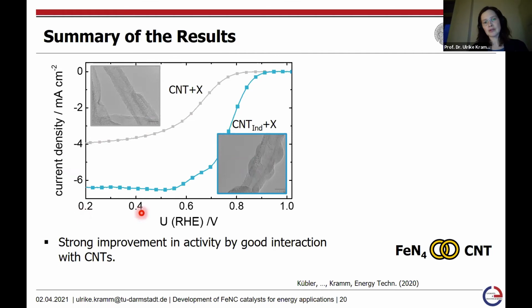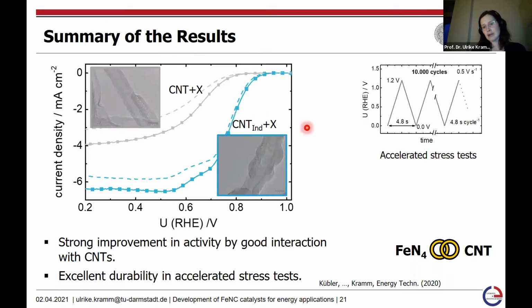For the oxygen reduction reaction, we have a standard potential of 1.23 volts, and that means you expect a low overpotential. This would be like for the blue curve, whereas the onset potential for the CNT-based catalyst material is much worse in comparison to this one. So this was already a nice result, and we were already quite happy about this, specifically also when Markus then performed some accelerated stress test.